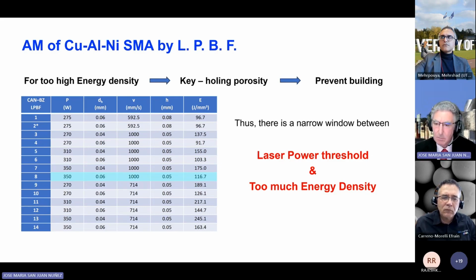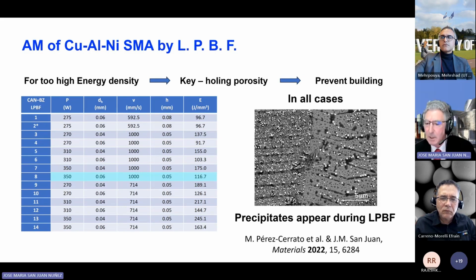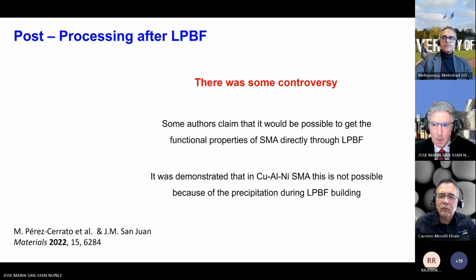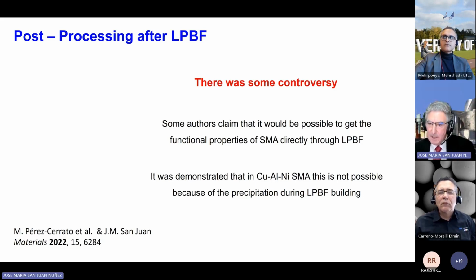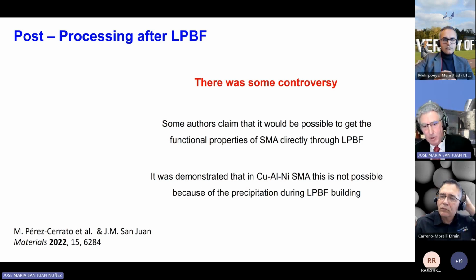However, in all cases, we obtain precipitates that appear during laser powder bed fusion. This problem was already indicated, published in a previous work, and is very important because it will destroy the functional properties of the shape memory alloy. So there was some controversy on this point because some authors claim that it would be possible to get the functional properties of shape memory alloys directly through laser powder bed fusion. But at least in copper, aluminum, nickel shape memory alloy, it was demonstrated that this is not possible because of the precipitation of the equilibrium phase during the laser powder bed fusion building process.